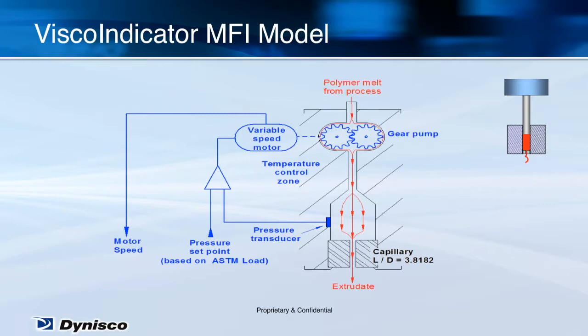In the ASTM mode of operation, the pressure defined by the load in the piston is specified in the ASTM method and created by controlling the gear pump flow rate using data from the pressure transducer. The material flow rate is calculated from the speed of the gear pump. A gear pump is essentially a positive displacement device that pumps the melt at a constant rate, regardless of the resistance to flow. By measuring the gear pump speed required to control pressure at the ASTM set point and knowing the pump flow rate, the visco indicator is able to calculate MFR directly as a function of pump RPM, given that the melt density is known.